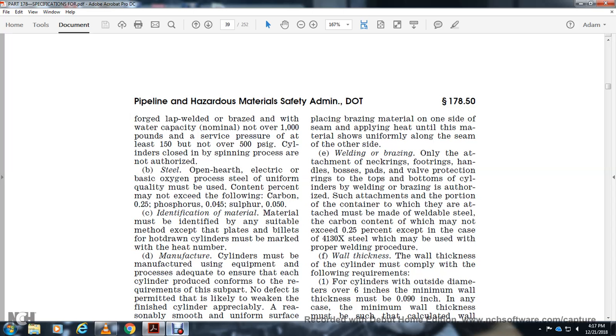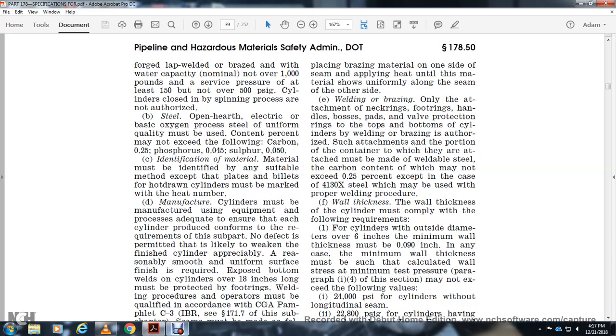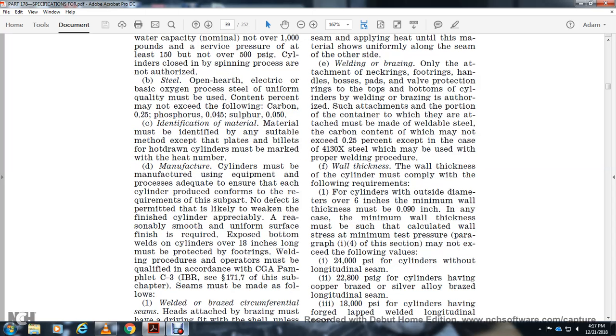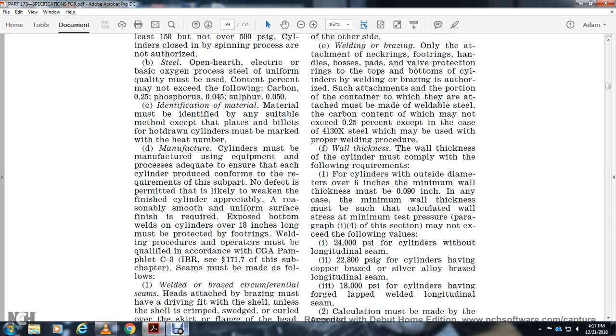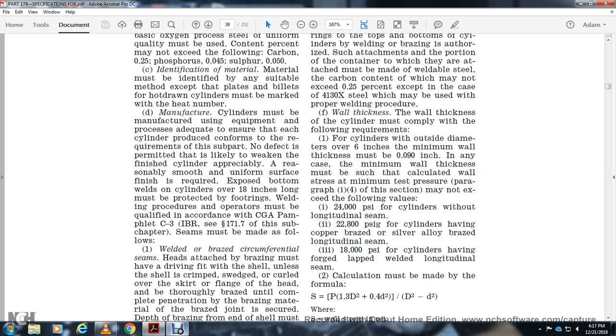Wall thickness for the cylinder must comply with the following requirements: for cylinders with an outside diameter over 6 inches, the minimum wall thickness is 0.090 inch, and in any case the minimum wall thickness must be such that the calculated wall stress at the minimum test pressure may not exceed the following values: 24,000 psi for a cylinder without a longitudinal seam; 22,800 psi for a cylinder having a copper braze; cylinder with alloy braze longitudinal seam, 18,000 psi; for a cylinder having a forge lap welded longitudinal seam, 2 calculations must be made.